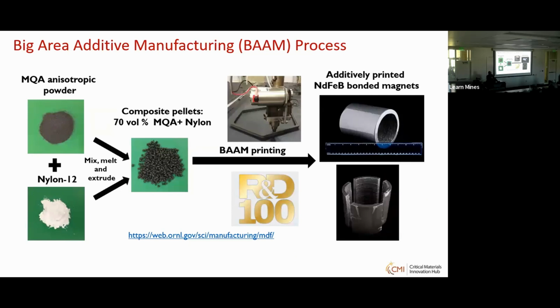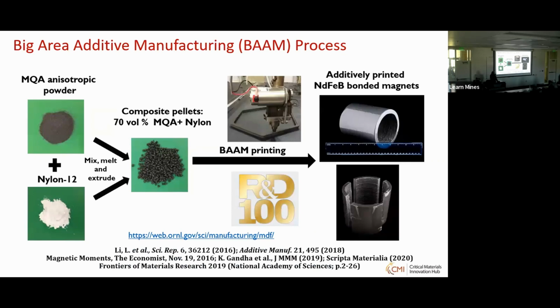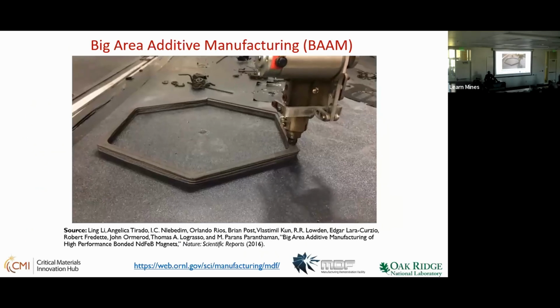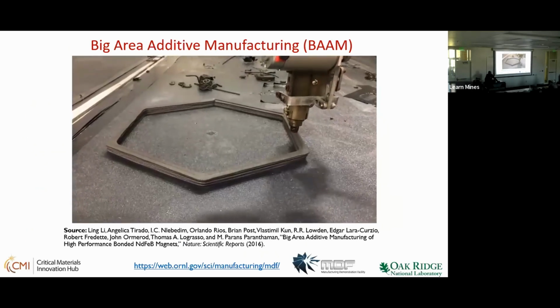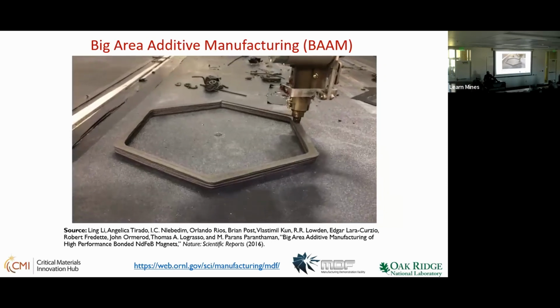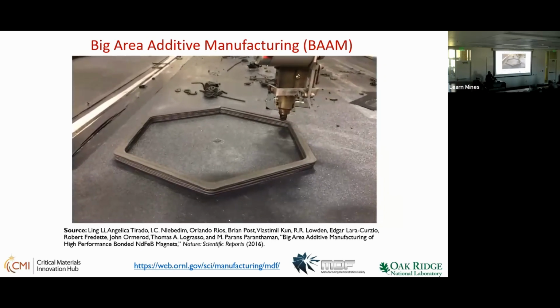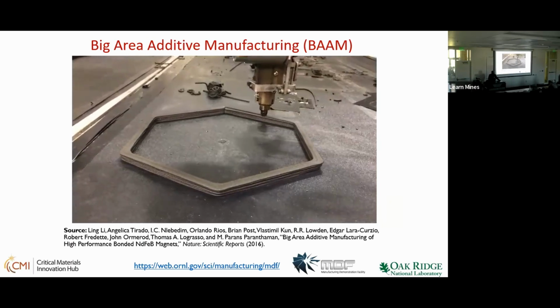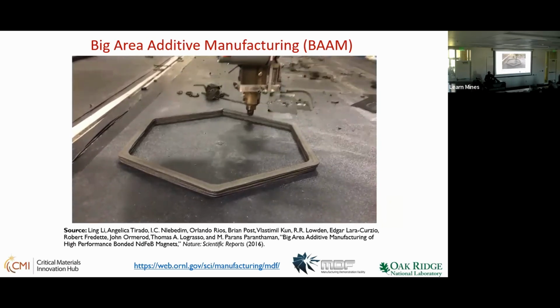We made unique shapes and sizes and properties. I think we won an R&D 100 award, and we published a lot of papers based on this method. You can see the video of printing. Once you do this printing, you can measure the mechanical properties. You can print fast, like 80 kilograms an hour, but you may lose surface quality, so you have to polish it a little bit.